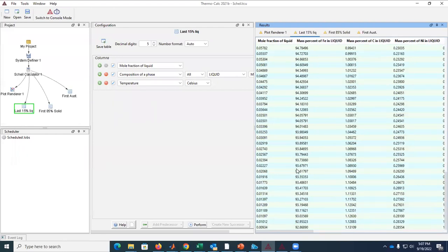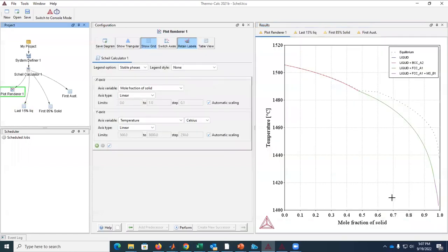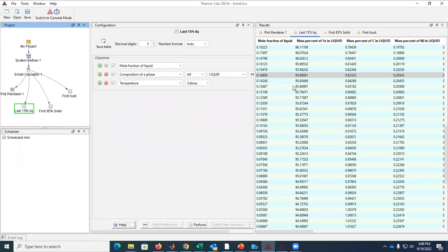On average, you are not going to get that because, again, you are at high temperature. So you notice here, 15% liquid is around 85% solid. If you have almost 100% liquid or 0% liquid, you have some time where the materials can diffuse at high temperature, and there are average values here. So again, some researchers have found in some papers that 15% liquid is a good point to assume the composition. So if you go to the table again, you are going to notice that you have a chemistry.